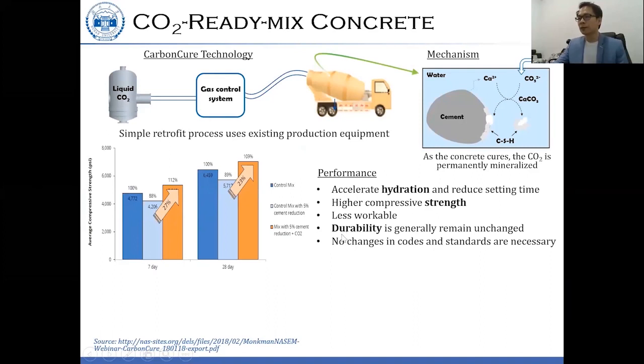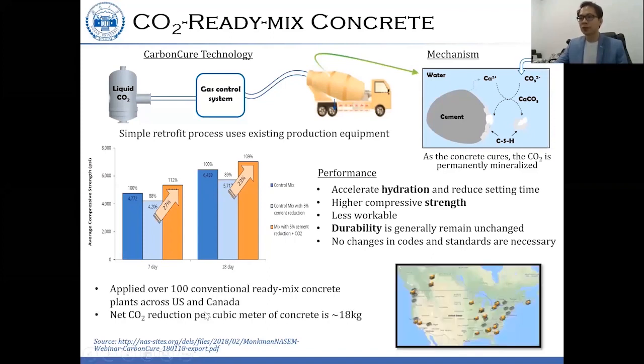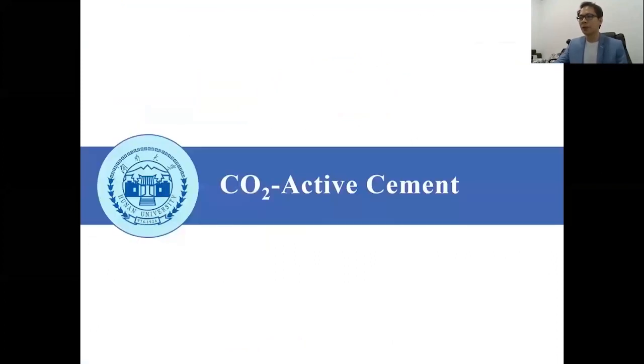They mentioned the durability generally remains unchanged, however, the workability is a little bit less than the conventional concrete. So the technology is already applied in over 100 conventional ready-mix concrete plants across the US and Canada. So they can reduce 18 kg of CO2 per cubic meter of concrete using this technology. Next, CO2 active material.